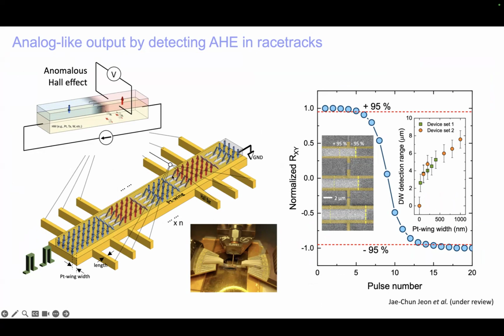Now we detect the anomalous Hall signal created by current passing through the magnetic material via the platinum Hall bars you can see here, platinum electrodes placed along the racetrack. It turns out, very interestingly, that by changing the width of this platinum wing, the Hall signal that is created can be used to detect the domain walls a long way from the electrodes themselves, which are labeled here by this Hall bar. So this is an amazing finding because it means we can actually see a domain wall everywhere along the racetrack by having a series of these electrodes to detect the Hall probe at different places along the racetrack.